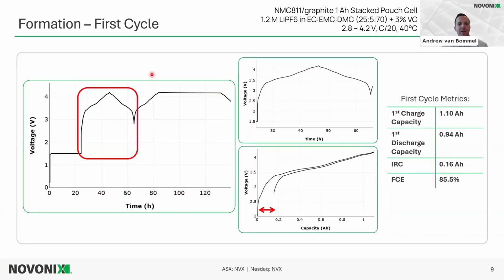Some more metrics during the formation. We do a C/20 charge and a C/20 discharge. So we have a charge capacity and a discharge capacity. If we fold that discharge capacity over on the profile, we could see the difference between the charge and the discharge there. That's the irreversible capacity, the IRC, 0.16 amp hour. And in this case, the FCE, the first cycle efficiency, is the ratio of the discharge capacity to the charge capacity. These are accounting for some of the losses that occur during that formation step, whether it be from the material or from the SEI growth. So this is 85.5. We hope that FCE will be really high, so we can compare that between cells. Again, we're just showing one cell for illustrative purposes here.